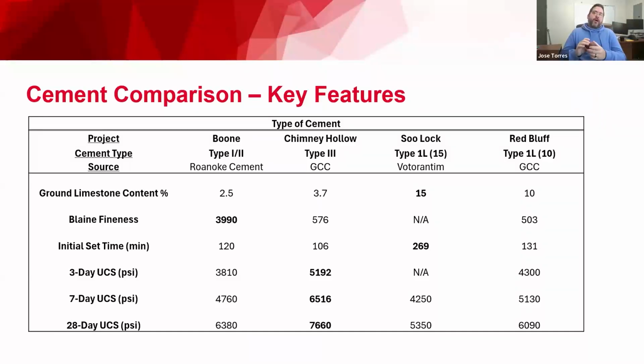Here's some initial set times as well of every cement that's out there, based on the manufacturer recommendations. And then there's some strength information for 3-day, 7-day, 28-day on what you can expect out of the cement to start with. Generally we can see that type 3 had the highest strength here on this table, followed by type 1-2, and then we have type 1L10 and type 1L15. I didn't put it in order, but that's sort of the order that the paperwork says it's going to be, right?